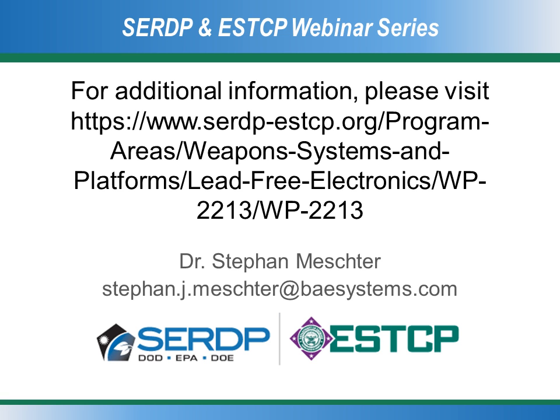Why not just coat with Parylene? You have cost and repairability as probably the two biggest issues. Certainly it can be done, but there are significant advantages to a spray-coated system, and of the spray coatings, the polyurethane family performs the best from current whisker testing. So you leverage ease of application, ease of masking, ease of repairability. I think those are all strong reasons to utilize a spray coat rather than a vacuum deposited coat, if you can.